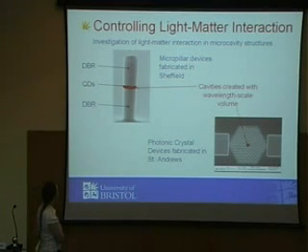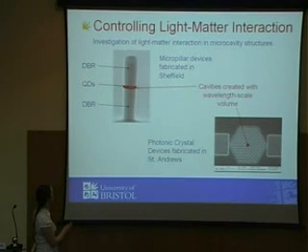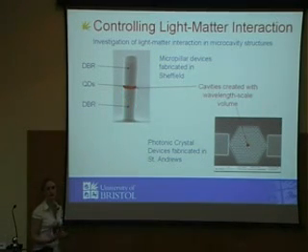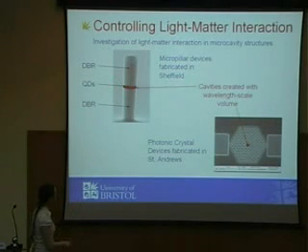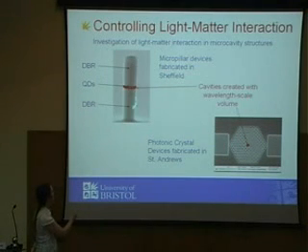I'm showing you two examples here. We have a micropillar device, which was fabricated in Sheffield. Here we have distributed Bragg reflectors, and they essentially act as mirrors, so they reflect the light downwards and upwards. We've created a small cavity here, which I've coloured in red. This cavity contains the light over a very small volume, about 1 micron across and about 10 microns in height.